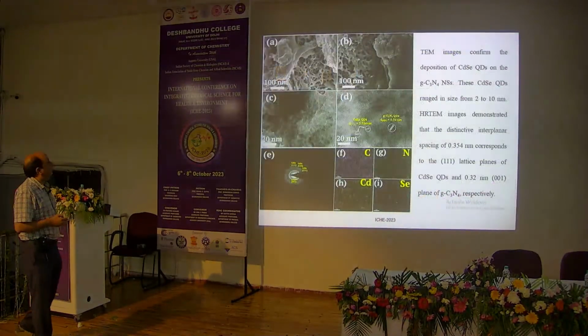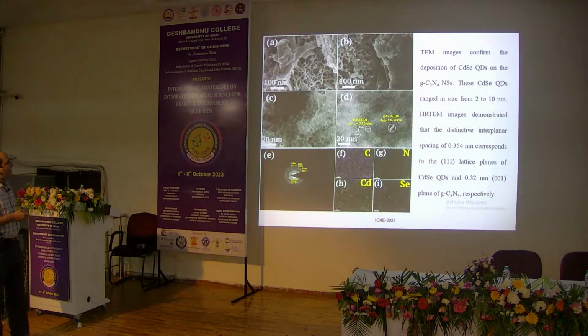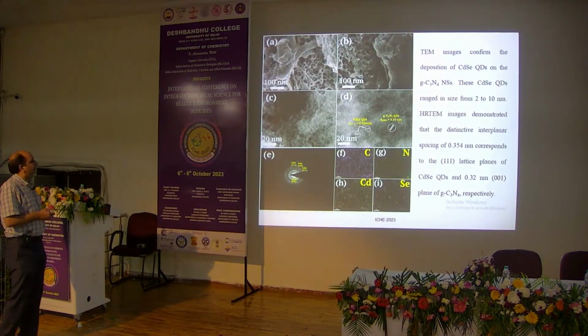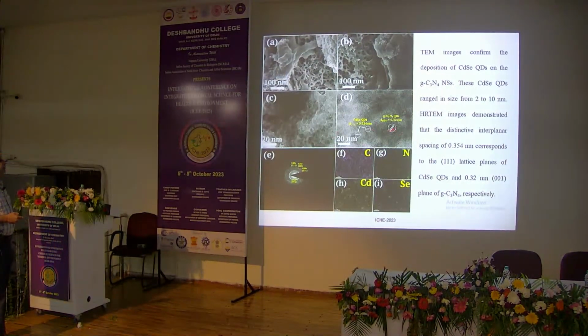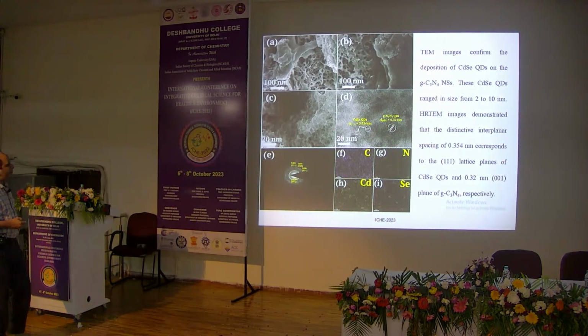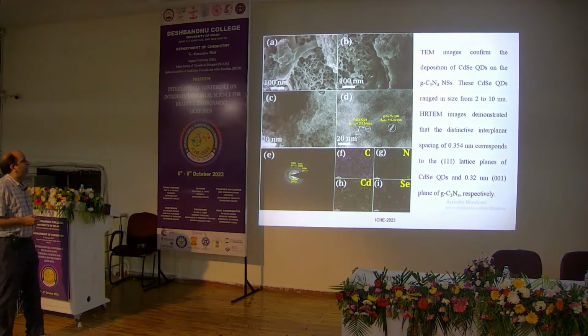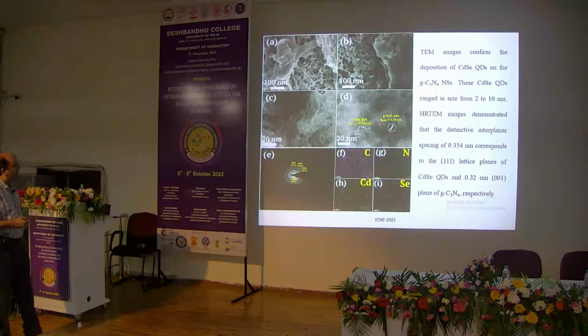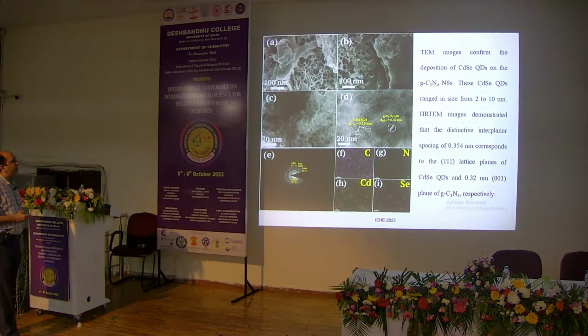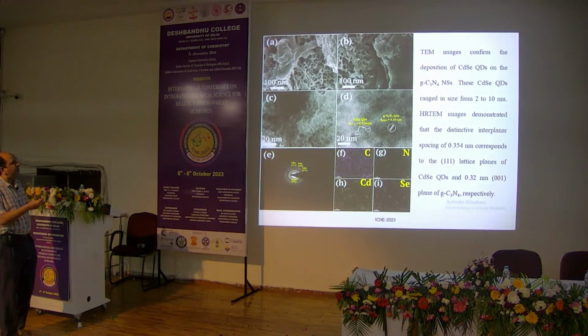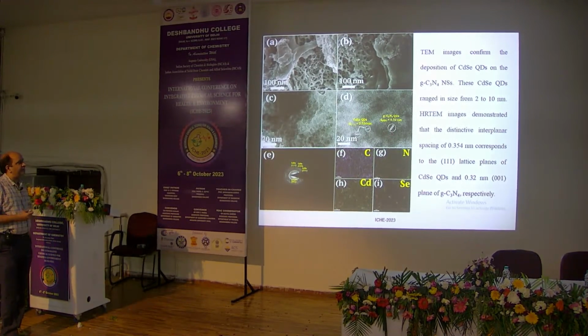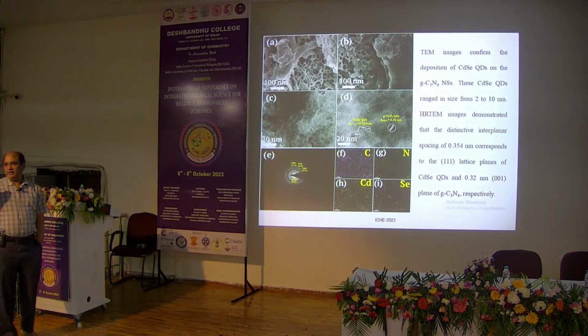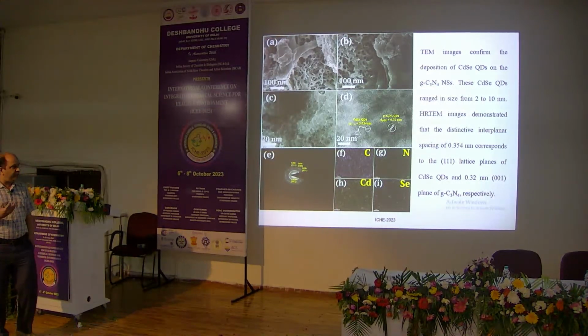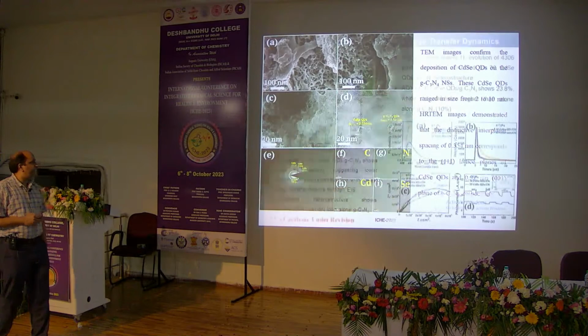Now coming to the main part, these are the detailed electron microscopic investigations, and if you see the high resolution transmission electron microscopy, then the different lattice fringes could be seen, one corresponding to the graphitic carbon nitride and another for the CdSe quantum dots. And we have matched these lattice fringes with our lattice interplanar distance obtained by using the X-ray diffraction.